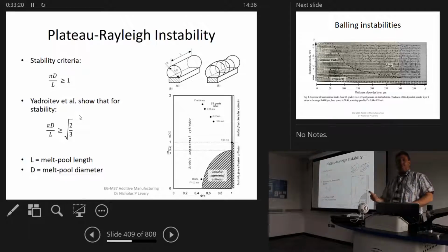So now, why is that important? If we have breakup into droplets, those balls could potentially be there and run off, so they're not going to be in the place where you wanted to put them. So controlling those instabilities is very important from the perspective of the process. Now, it's been shown theoretically that for a long column, there's a stability criterion which is determined by the diameter and the length of the column. And this has been modified more recently to say that if that was greater than or equal to 1, then you would have an unstable melt pool. For powder-based methods, it's been shown that if that is greater than or equal to the square root of 2 over 3, we actually have instability.